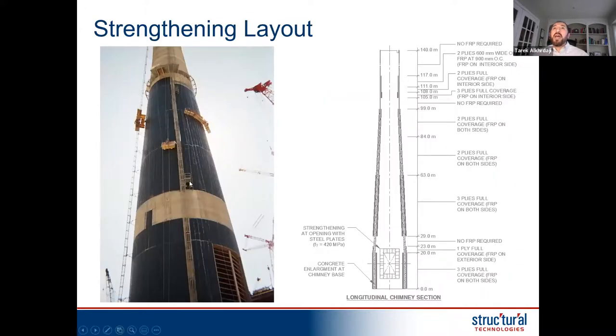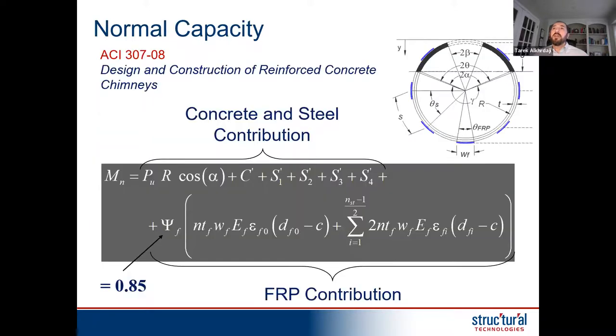Here I wanted to show you a chimney, which is a big vertical cantilever going in bending due to seismic code requirements. It has a flexural deficiency in bending, right? So FRP was installed externally in the locations where it doesn't have adequate flexural capacity based on the demand provided by analysis. And that FRP was tailored from 3 layers to sometimes 2 layers, in some areas 1 layer, or no FRP. So you can easily change that, and it was applied to meet the standard.